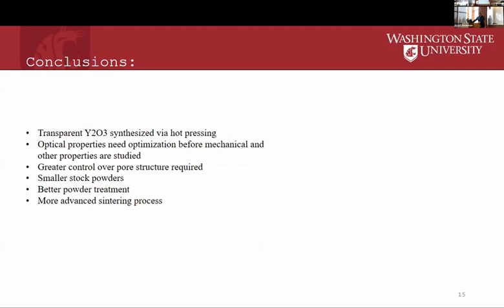Question: But pycnometry still doesn't account for closed pores, correct? Yeah, if your porosity is closed off, or the channels in your material are too small for the helium to get into, then you have no way of really knowing or seeing that. Whereas if you have a lot of surface defects, the helium gas can get into places that water is too large to get into. You might see a significant difference—if you have a lot of interconnected channels, water probably won't be able to get into them, but helium gas will, and you'd see a much closer theoretical density than you would otherwise.